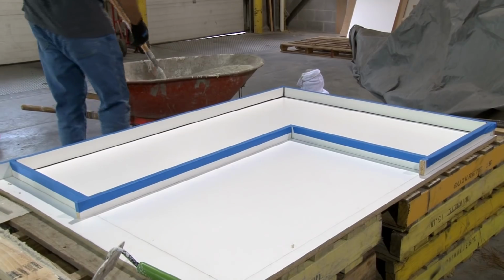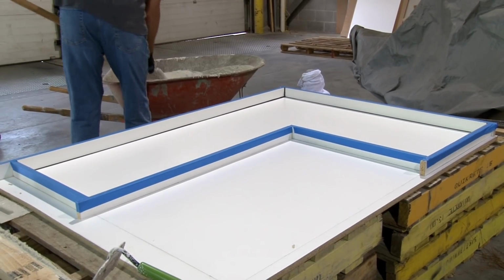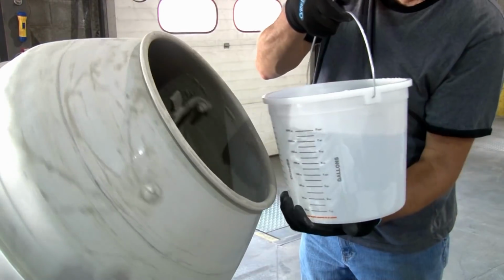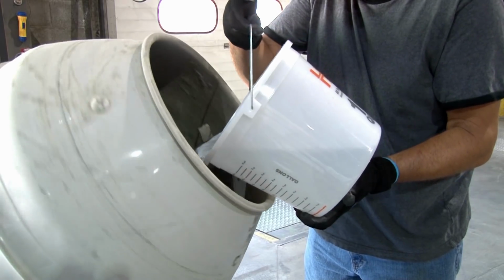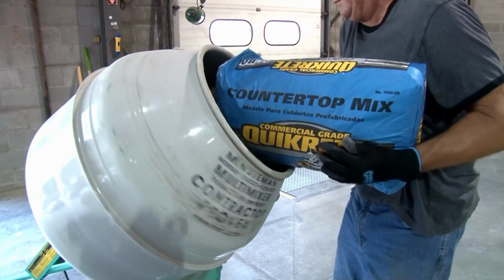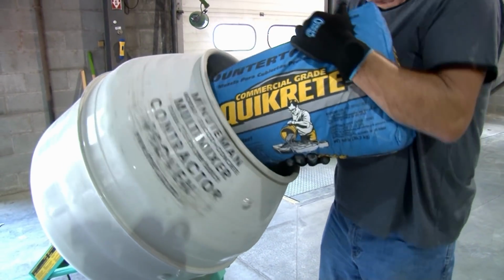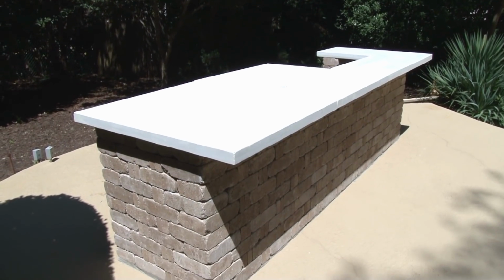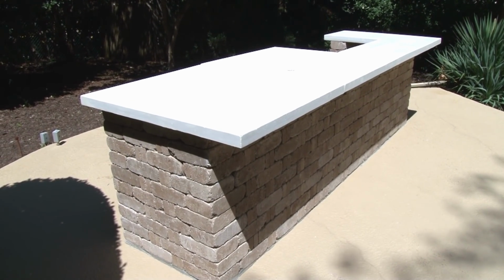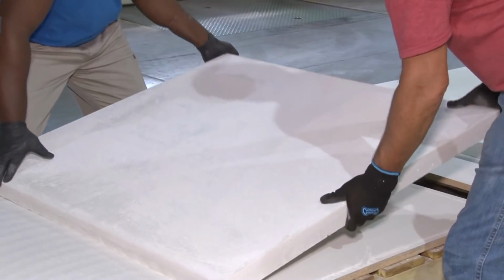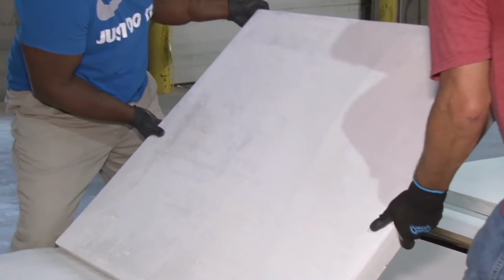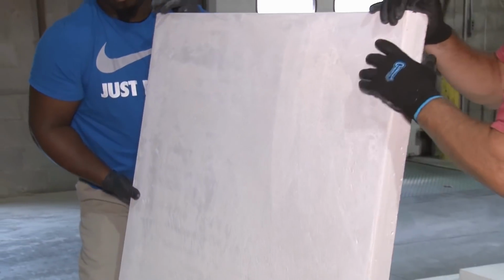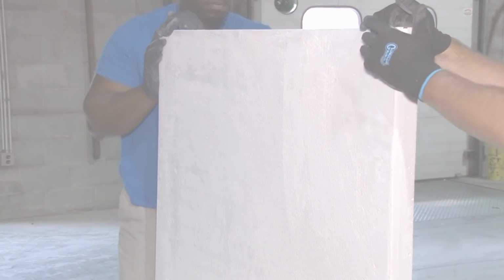Now the form is ready for the countertop mix, which can be mixed using a standard drum mixer or in a 5-gallon pail with a 1/2-inch drill mixer and mixer blade. QUIKRETE Countertop Mix is designed specifically for countertops. The high-density, high-strength concrete mix can be removed from the forms in just 18 hours and achieves over 6,000 psi in 28 days.